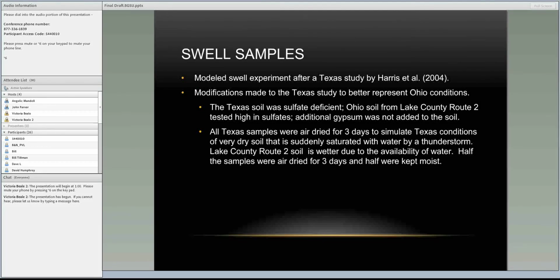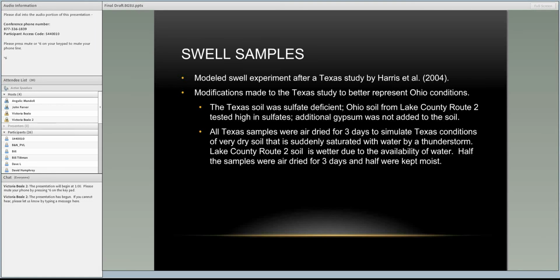Whereas in the Texas study, they added additional gypsum, fine-grained and coarse-grained, because their soils are sulfate deficient. Their soils are very dry there, and then they'll get a heavy saturation of water from a thunderstorm. So they took all their samples and air dried them for 3 days. What we did to be consistent with that study was take half of our samples and air dry them for 3 days, but the other half we kept moist because we felt that more represented Ohio conditions in Lake County.